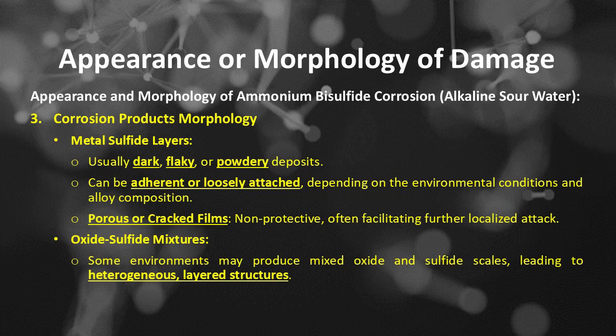Appearance and morphology of ammonium bisulfide corrosion or alkaline sour water. Number 3 is corrosion products morphology, which includes metal sulfide layers, usually dark, flaky, or powdery deposits that can be adherent or loosely attached, depending on the environmental conditions and alloy composition. Porous or cracked films are non-protective, often facilitating further localized attack. Another corrosion products morphology is from oxide-sulfide mixtures. Some environments may produce mixed oxide and sulfide scales, leading to heterogeneous, layered structures.